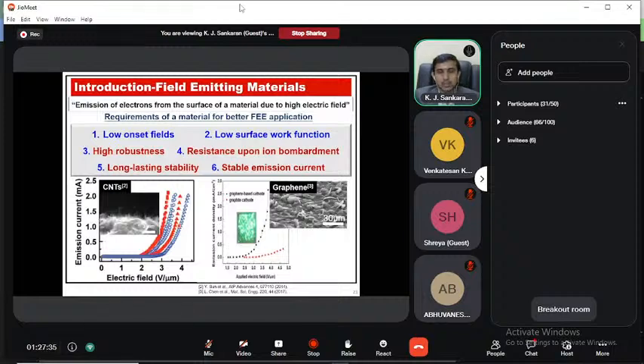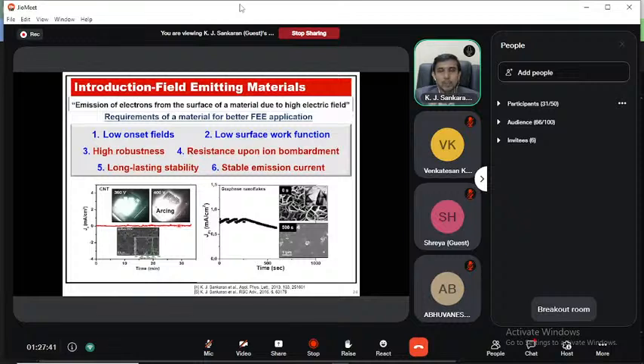You can see the carbon nanotubes and graphene showing a turn-on field of less than 1 volt per micrometer, but when you apply a high voltage or a longer lifetime, these materials cannot withstand the plasma environment or the bombardment of the ions. So you can see that CNTs can degrade even at 400 volts, and carbon nanoflakes were completely degraded or etched out by the electron emission even at 500 seconds. So we need a stable electron emission material.